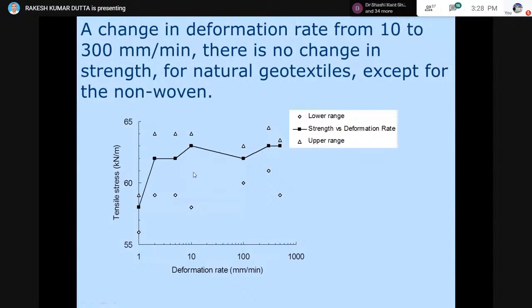So this indicates that the strength of these materials can be measured by using a strain rate of 10 mm per minute, and this 10 mm per minute is basically the recommended value for the testing of the polymeric geosynthetics, which is given in the ASTM standard. So that means for the naturally available coir geotextiles, especially the woven kind of geotextiles, the same strain rate we can basically use for testing the tensile strength of these materials.